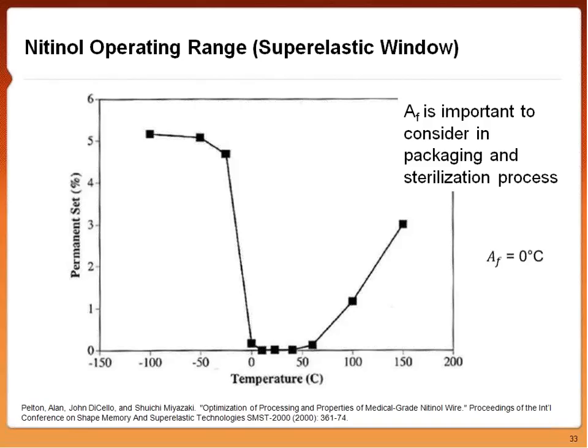Typical EO sterilization maybe happens around 60 degrees Celsius. And when you look at this graph over here, at 60 degrees C, you might have a little bit less than 1% permanent set in your material. Again, this is an austenite finish temperature of 0 degrees Celsius. We look on the graph over here, we have high permanent set at these lower temperatures because we know we're operating in our Martensite phase. Once we hit 0, we have almost no permanent set because we're operating in our superelastic phase.